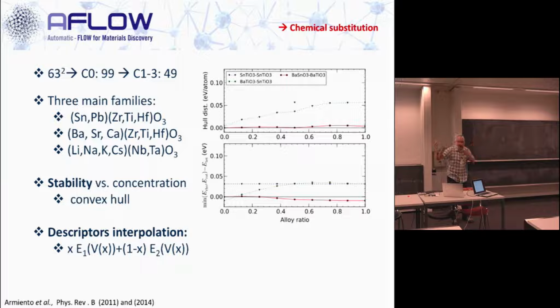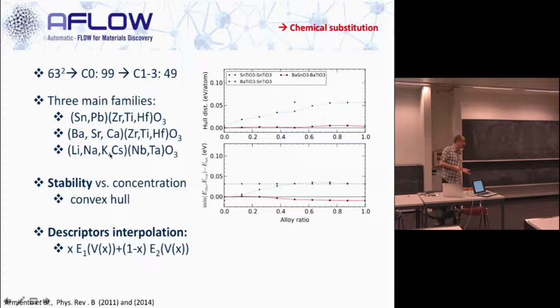Actually, one was discovered exactly when we were working, that exhibits good piezoelectric property. By playing carefully between the pairing of this, we could also come up with some new compositions. Okay? But the point is that we didn't expect to make a great discovery. The reason is that perovskite has been studied so much that high throughput was not ideal for this. This was mostly a validation process. But we validated very carefully that our criteria, C0 to C3, are actually working and distill everything that we know. Okay? And this is a value.